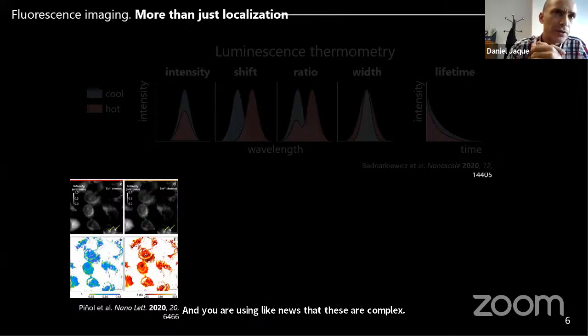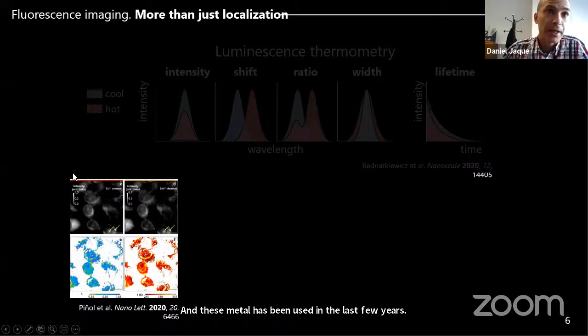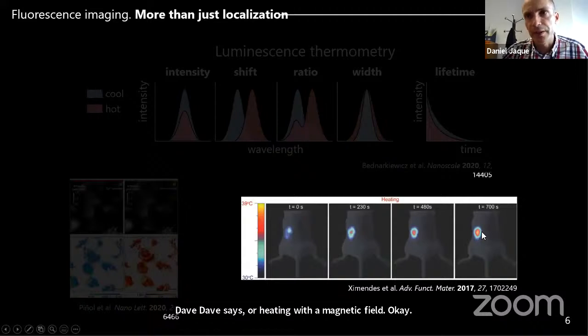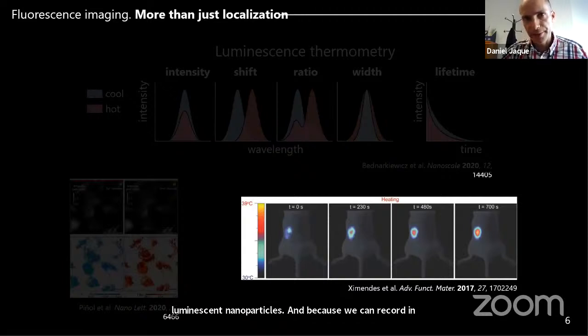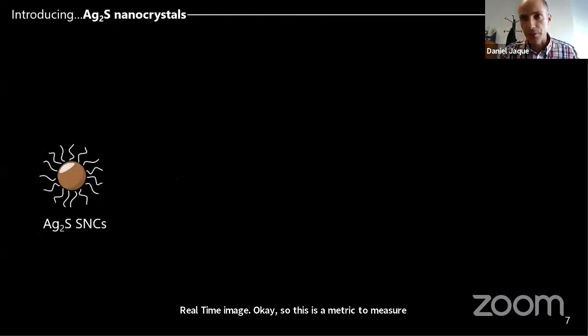And this method has been used in recent years in very challenging applications. For example, in this work, authors were able to see the temperature inside a living cell by analyzing the luminescence of the nanoparticles, and they were able to see how the cells are heating with a magnetic field, okay? And also in our group, we were able to measure the temperature of an internal organ of an animal by using luminescent nanoparticles. And because we can record in a very fast way, we can do real-time imaging, okay? So this is a method to measure the temperature of internal organs without touching anything, without contact, okay?